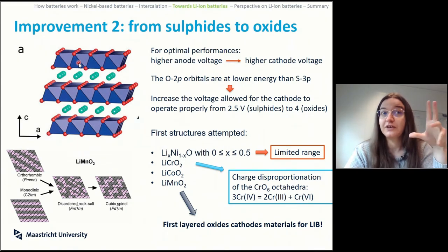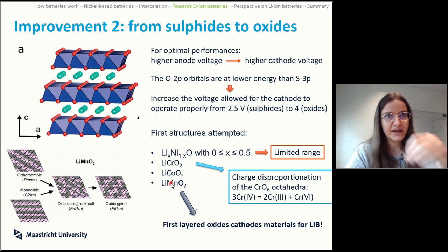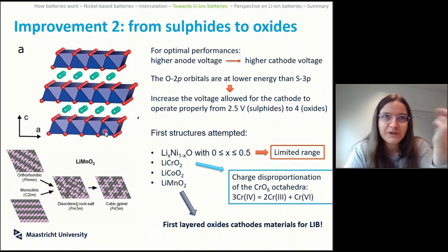It's important that you manage to order this thing very well, but this can be done because cobalt and manganese have a size that is completely different from the size of lithium, so you do not have the risk of finding lithium in here. The lithium will always be in here. So with a very nice order, you get a very nice performance. This encountered some resistance because it was a discharged cathode.